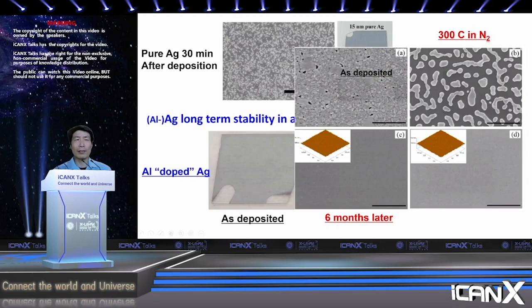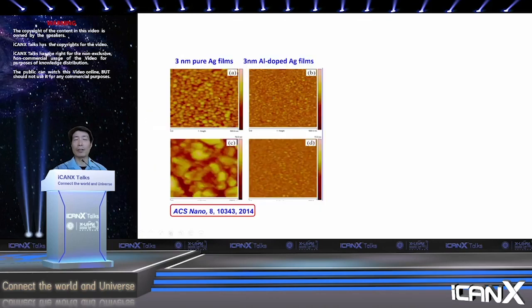So we did a little study on the mechanism. For example, if you start the film deposition and stop it at, let's say, three nanometers, and use AFM to take a look, you can see that pure silver already starts to grow very large grains. On the other hand, on this aluminum-doped silver, it's a much smaller grain size, and very distributed. So on top of this, the crystal won't grow big. You can see that the crystals on the left are very big, and on the right much smaller. This is discussed in more detail in this ACS Nano paper.